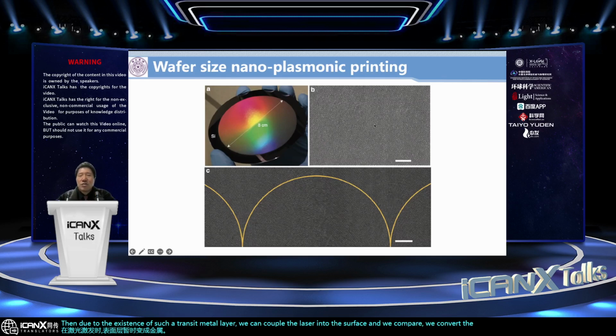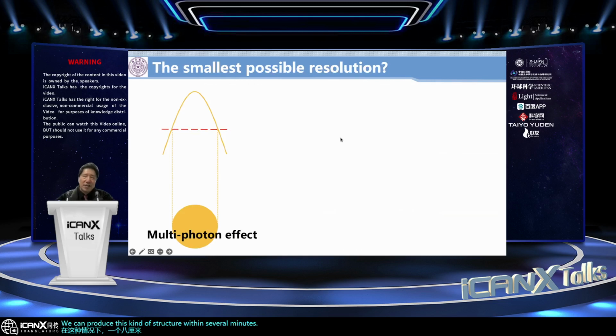Then we control the light intensity. We can brush the nanostructures with very high efficiency. In this case, on an 8 centimeter wafer of silicon, we can produce this kind of structure within several minutes. The efficiency is also very high.